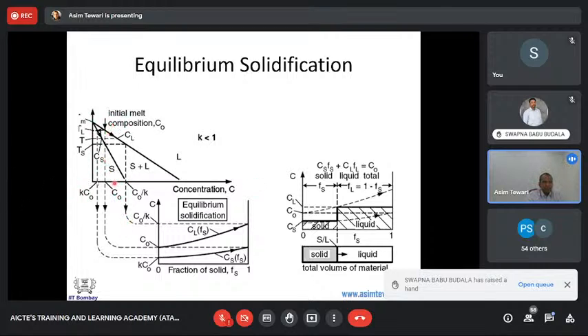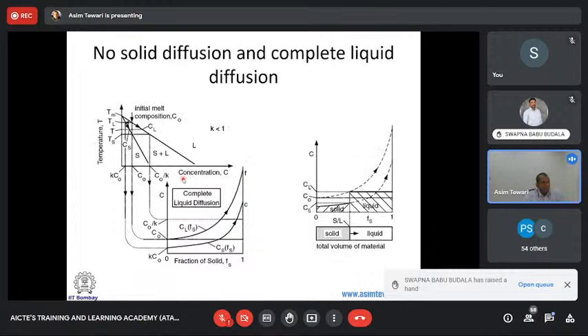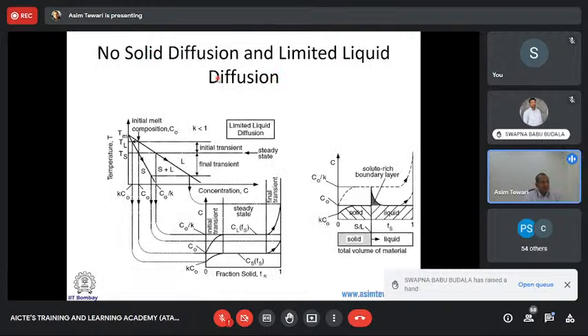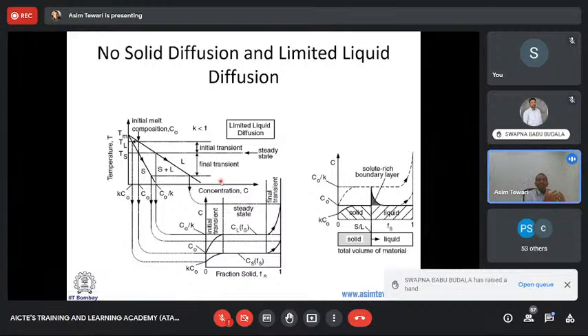So what I want you to appreciate is that depending upon how you are cooling, you will have segregations. If you think about this composition C0, when you're cooling down, your liquid will initially be at this temperature where the first solid will form, and the final solid will be this. And thus you'll have a gradient in your composition. So the solid will not always be of the same composition. Depending upon the rate at which you're cooling, you could have no solid diffusion and complete liquid diffusion, or no solid diffusion and limited liquid diffusion. All of these things can happen, and this is how the chemical profile of the solid and liquid would vary. So you need an intricate understanding of solute partitioning in the phase diagram to appreciate that.